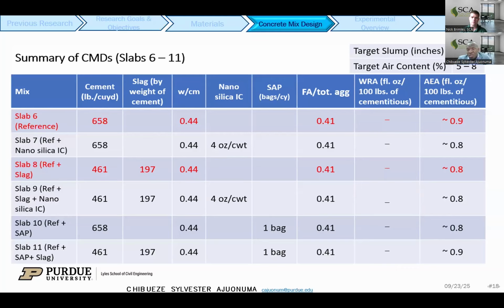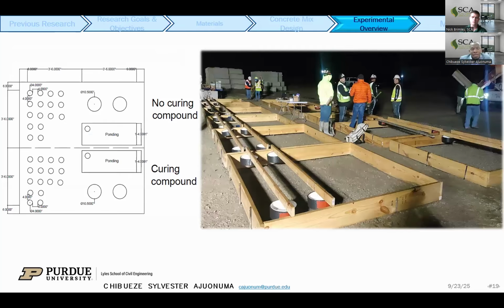And I also want to emphasize that no superplasticizer was used, no high range water reducer was used for this mix, because we employed the services of a commercial concrete mixing company for this project. And this is a schematic of the slabs we made in the field. We were able to make an 8 feet by 8 feet by 10 inches formwork for the concrete slabs, and then there was also an improvisation for 10-inch by 4-inch diameter discs, which we used as the specimens for the scaling resistance.